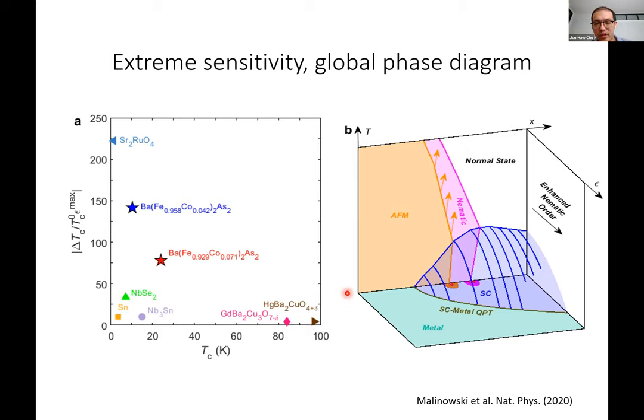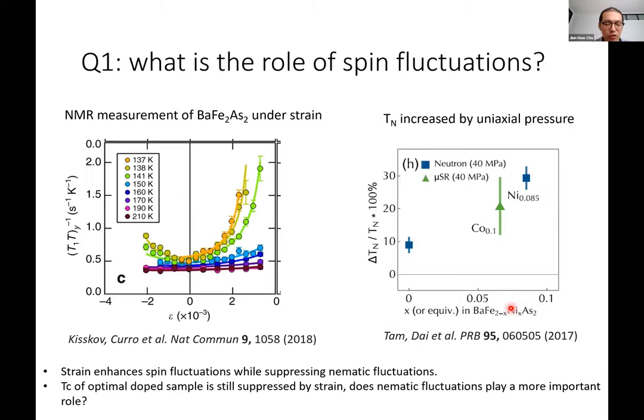Okay, and then finally, this very strong sensitivity allows us to construct this three-dimensional phase diagram where, as Pengcheng pointed out, TN increases, and also we can reach another quantum phase transition by suppressing the superconducting dome all the way to zero, achieving a superconductor-metal quantum phase transition in a three-dimensional material. So a few outlooks. First of all, an obvious question, the elephant in the room, is what is the role of spin fluctuation?